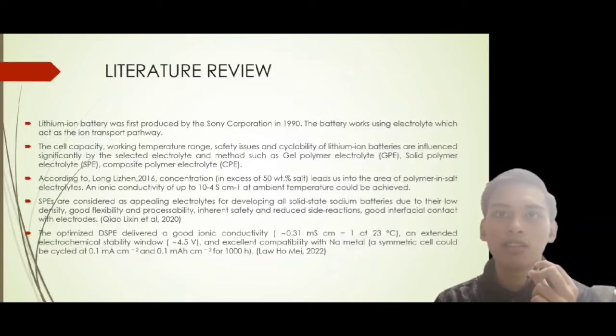According to Law Ho Mei 2022, the optimized DSPE delivered a good ionic conductivity of 0.31 millisiemens per centimeter at 23 degrees Celsius, an extended electrochemical stability window, 4.5 voltage, and excellent compatibility with natrium metal. A symmetric cell could be cycled at 0.1 milliampere per square centimeter and 0.1 milliampere hour per square centimeter for 1000 hours. That's all from me.